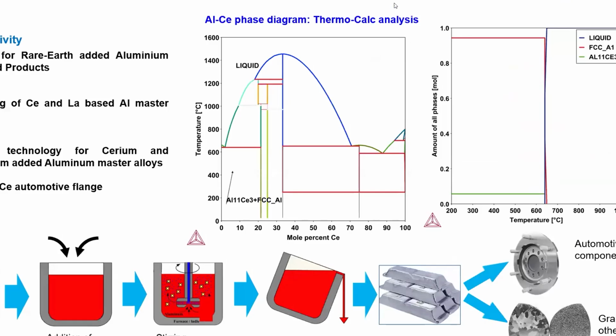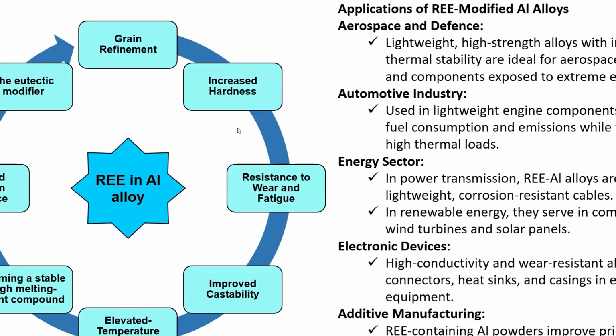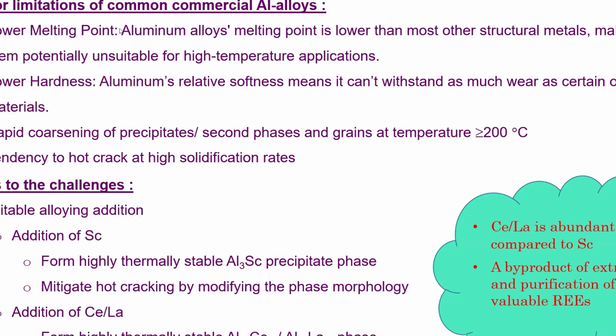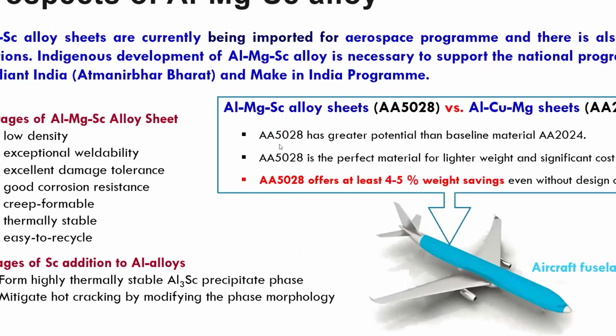We have also done these rare earth added aluminum alloys, because rare earth addition to aluminum alloys will improve the strength of the material by reducing the grain size. And if you reduce the grain size, then there is increased hardness, increased wear resistance, improved castability, and elevated temperature stability, because of the formation of high temperature phases. Normally aluminum has low temperature phases which are formed. But for example, in aluminum scandium alloys, Al3Sc is a highly thermally stable phase. Similarly, in the case of cerium alloys, it's Al11Ce3. All these alloys have highly thermally stable high temperature phases. Maybe I will not go into the detail of that.